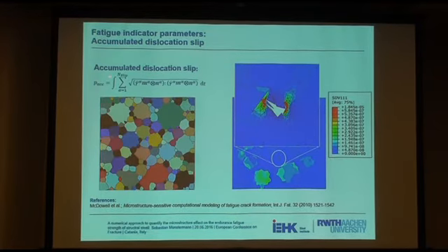And then we had to think about how to quantify the relevant loads. Of course, this is done with fatigue indicator parameters, and as this early stage of fatigue damage is very much related to the slip irreversibility, we believe that the accumulation of dislocation slip is a suitable fatigue indicator parameter for this early phase of fatigue damage.